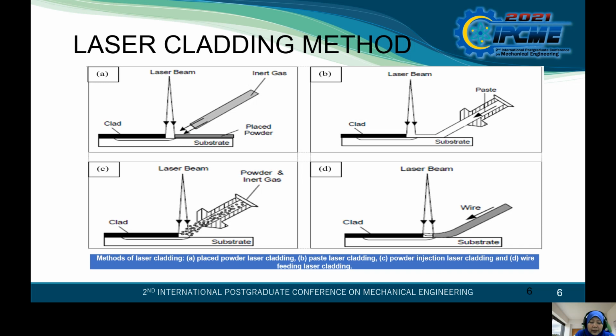One of the techniques to modify or improve surface properties in advanced manufacturing is laser cladding process. The advantage of implementing laser cladding are improved grain size, increased hardness, minimal dilution, and produce new surface properties. Laser cladding used a laser as heat source to produce the desired clad layer during laser processing. The deposit material can be transferred to the substrate by several methods as shown in figure A, B, C, and D. Figure A shows pre-placed powder method, B, paste powder on the substrate, C, powder injection, and D, wire feeding for laser cladding technique. Laser cladding with powder injection is proven to be the most effective method to produce clad layer. During cladding process, the laser beam melts the powder particle and produce thin layer on the substrate.